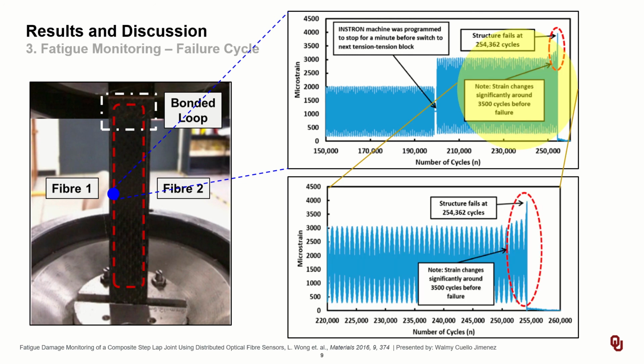Now zooming into the last 35,000 cycles, results reveal that the failure occurs after about 254,000 cycles. The strain gradually changes over the last 3,500 cycles prior to failure. Perhaps more importantly, the ability of the distributed optical fiber system to measure strain change before failure takes place, and the location of the fracture point, can be used as an indication of damage along the structure.